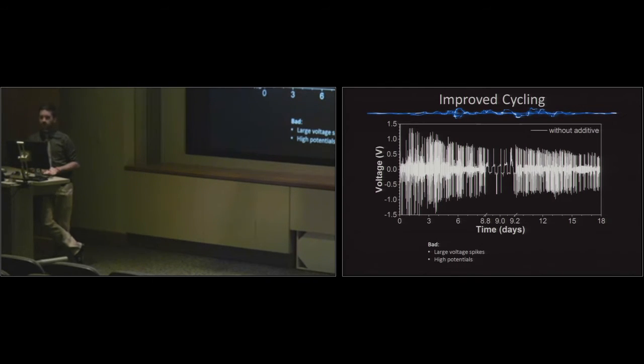And so a typical lithium-ion battery electrolyte will have about a concentration of 1 molar of a lithium salt. I added in this additive that was about 100 times less the amount of that salt. And you can see the results are pretty astounding.